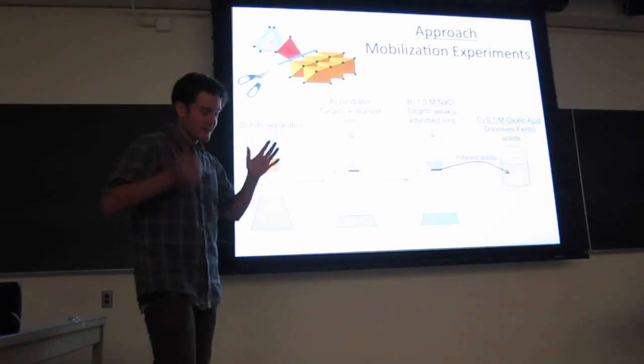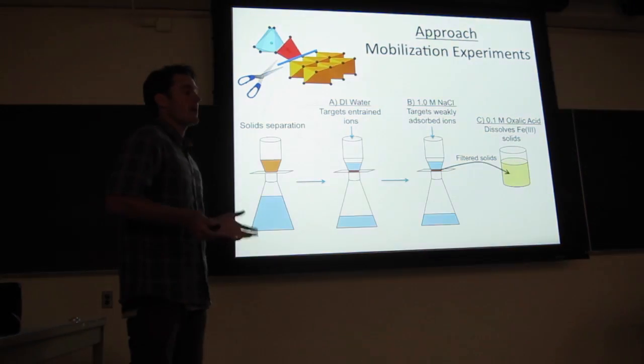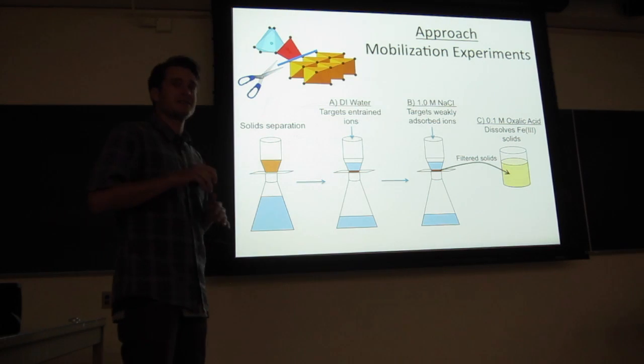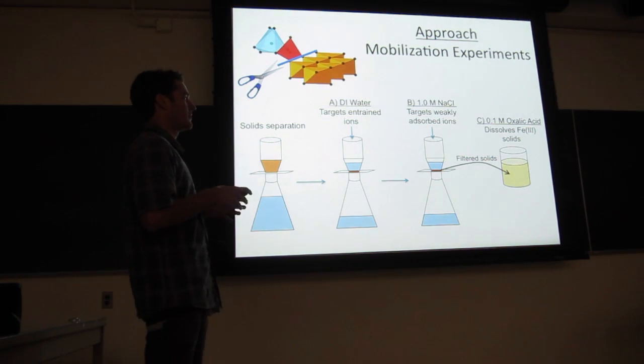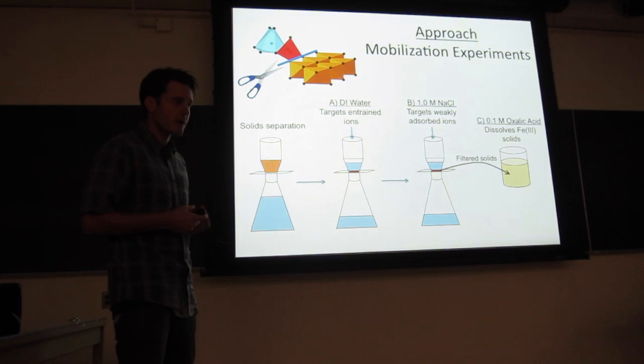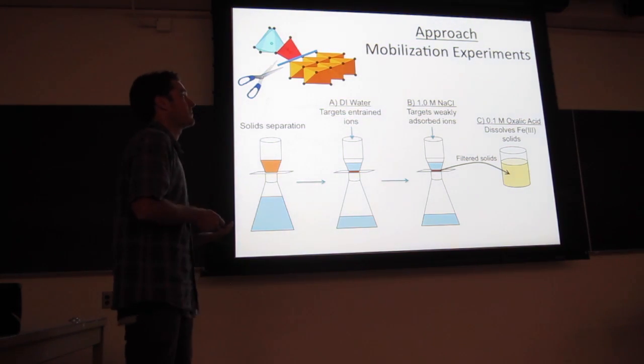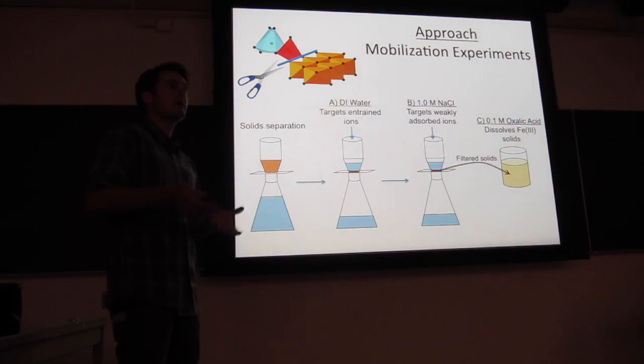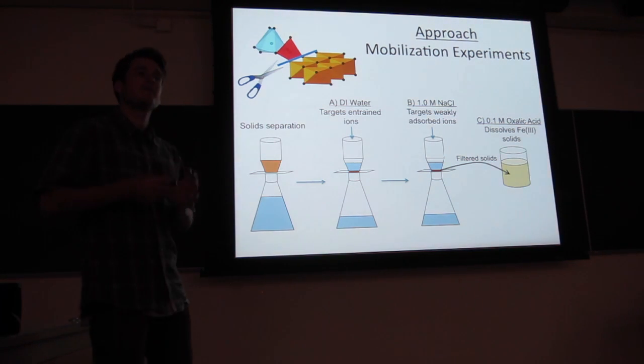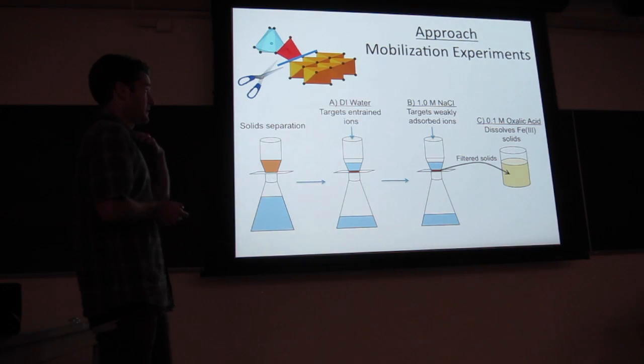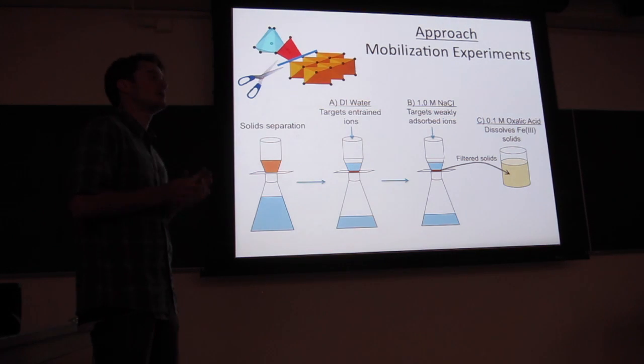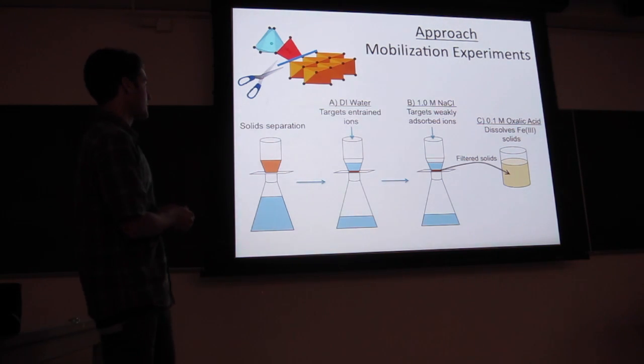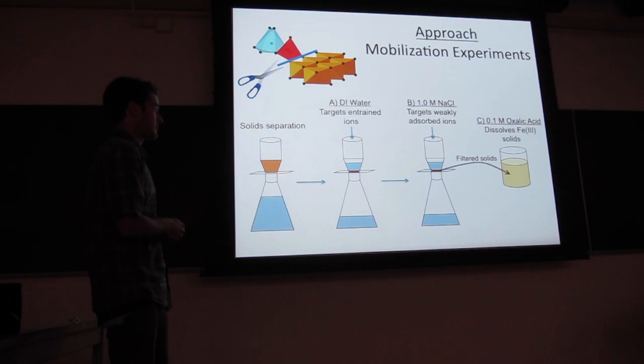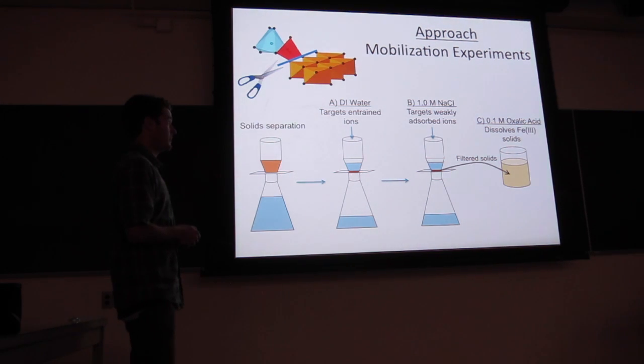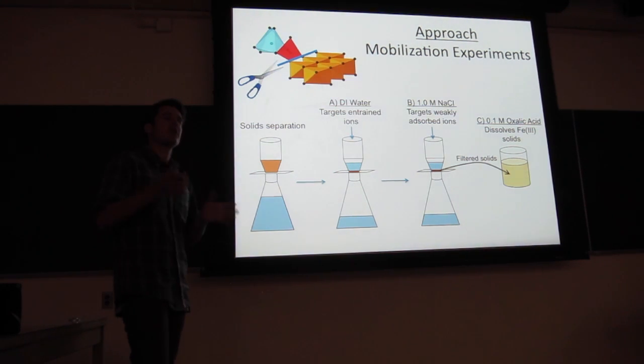All right, so now that we have a good idea about the macroscopic picture of what's happening in the system, we can start to approach the chemical bonds that are happening in our system. So we know that arsenic and phosphate and calcium are being taken up by the oxide. We want to understand how they're being taken up and the strength of the bonds that are formed. So what we're doing here is using chemicals to probe the strength of the bonds. In this approach, we filter the solids and leave the solids on the filter membrane, and then we pass a series of solutions through, which are designed to target different kinds of ions.